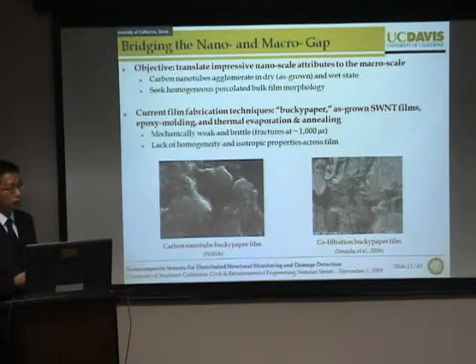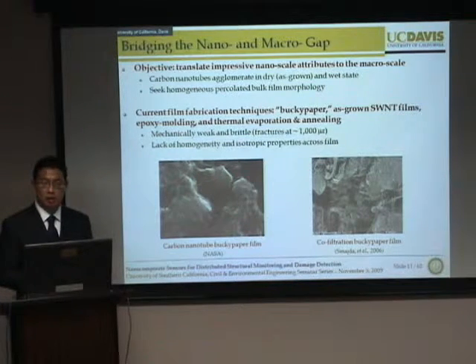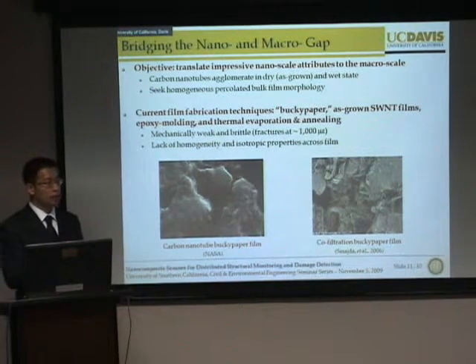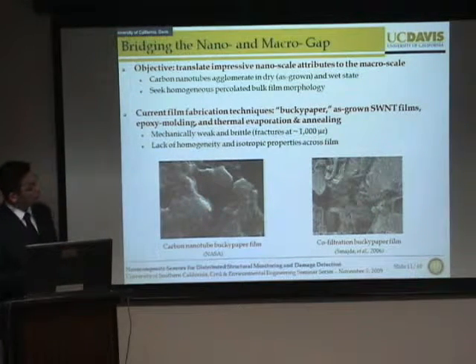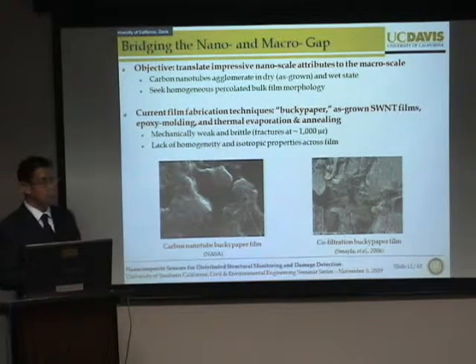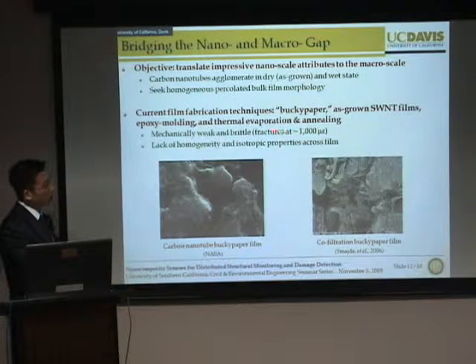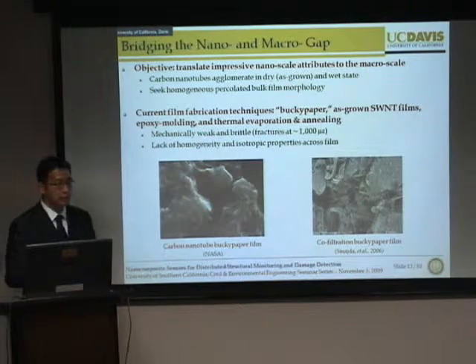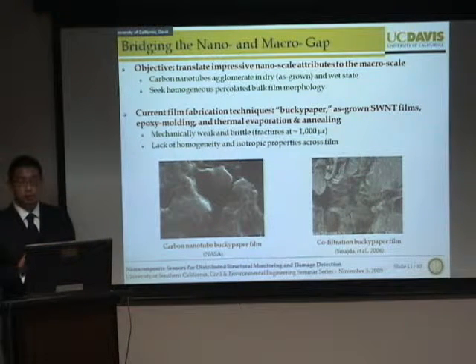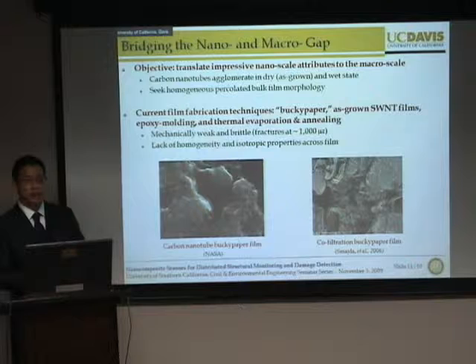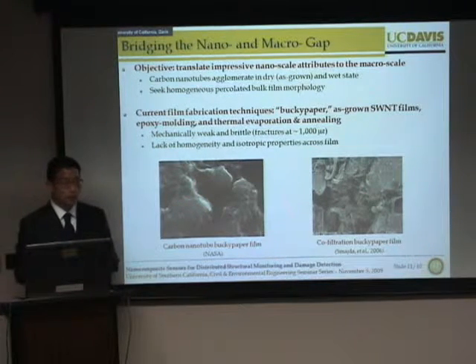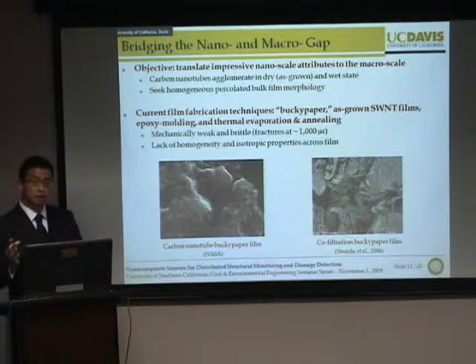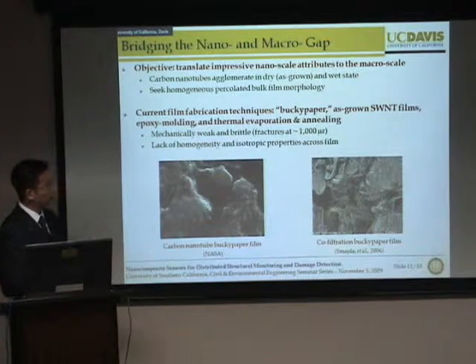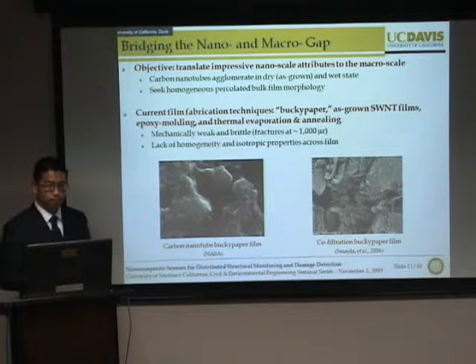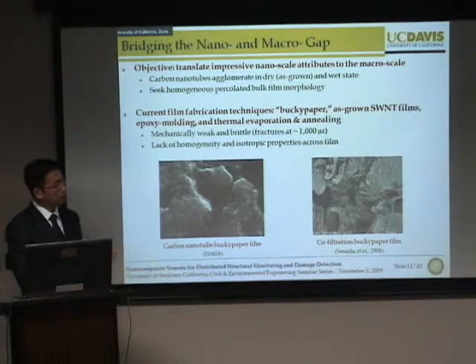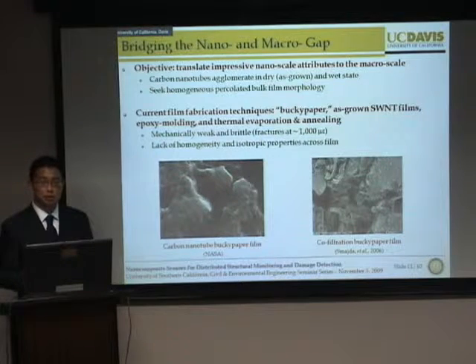Now, in order to do so, one of the most straightforward ways to accomplish this goal is to combine carbon nanotubes into some composite thin film system. And the current thin film fabrication techniques that have been able to achieve this goal are namely bucky paper fabrication, and that is to separate individual carbon nanotubes in a solution and then vacuum filter it and then dry the filter to create this thin film structure. Other techniques include epoxy molding, that is to mix carbon nanotubes with some epoxy resin and cure it, or even thermal evaporation and annealing. But unfortunately, these different thin film fabrication techniques are essentially brute force techniques.